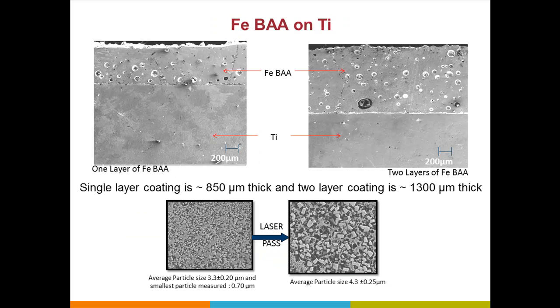If we look at it on titanium, this is a coating on titanium. Again, we can see there's some bubbling effect because they are not good conductors, and at the same time they absorb laser so much that we have to lower the laser power. But this is the coating, and this is the titanium substrate underneath. And again, if we heat treat it, or laser heat treat with the laser pass, we can vary how much crystallinity we want or what kind of crystalline shapes we want and things like that.